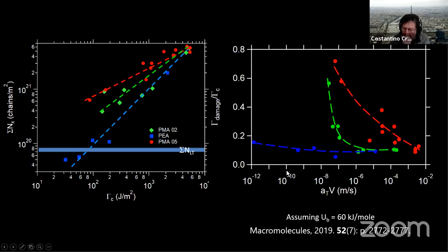But another way to plot the data is to look at the fraction of energy due to damage or bond scission relative to total energy. In this case, we have to assume an energy per bond. So here I took the 60 kilojoule per mole of Steve Craig's paper. And if we do that, we see a clear trend: going from high velocity, so high viscoelastic dissipation, to low velocity, the fraction of energy due to bond scission increases.